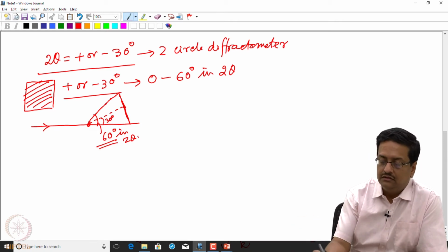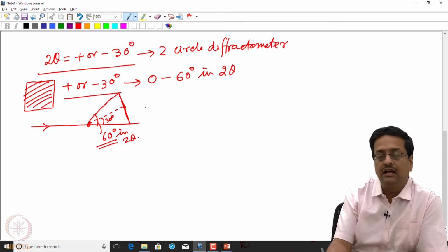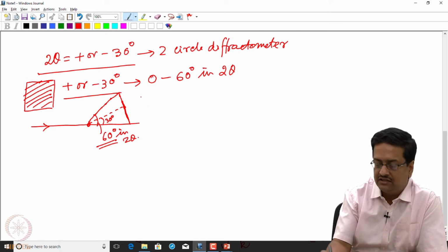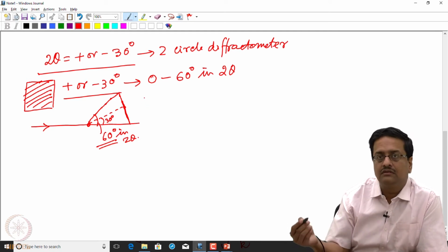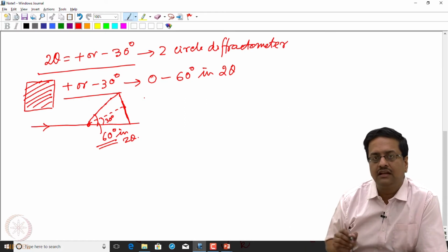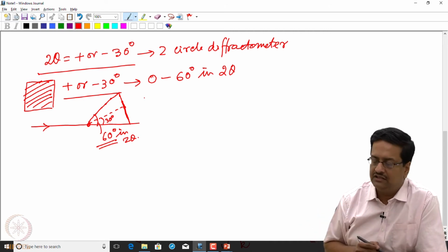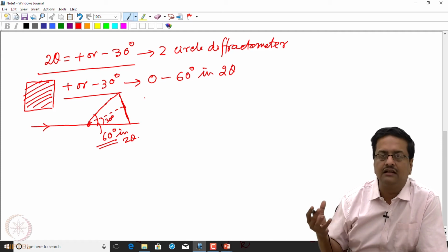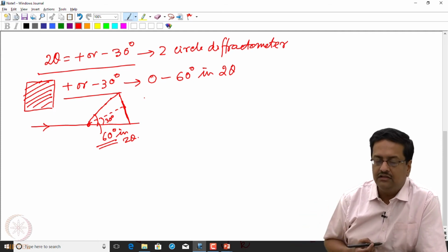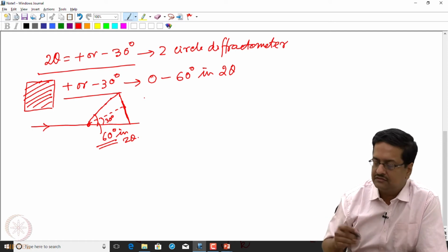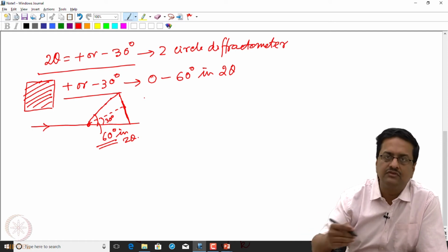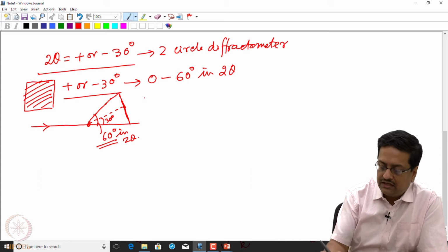And what is the limit for IUCR using molybdenum data? Mind you, for routine single crystal X-ray diffraction, everyone uses molybdenum because it has much higher penetrating power and gives much less absorption, and it can then collect the required data with less amount of 2 theta span. So we collect this data using molybdenum radiation,